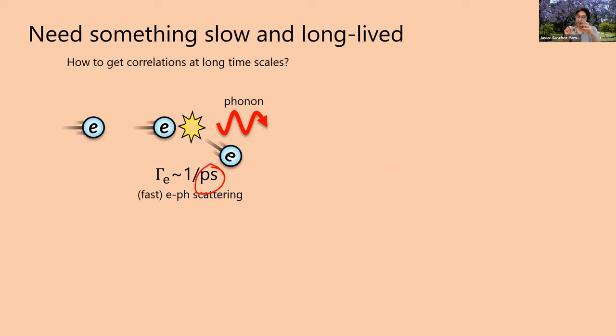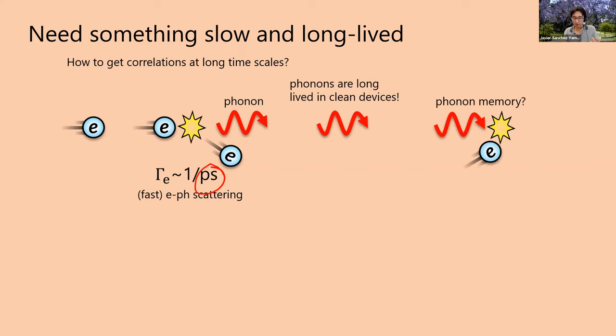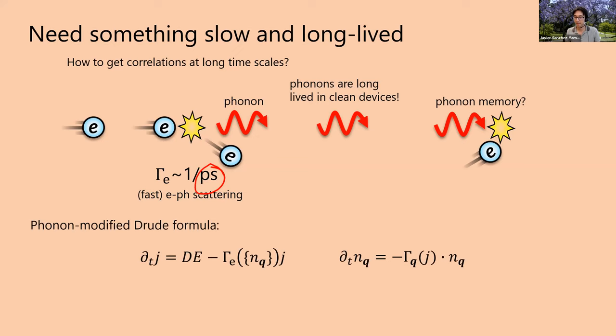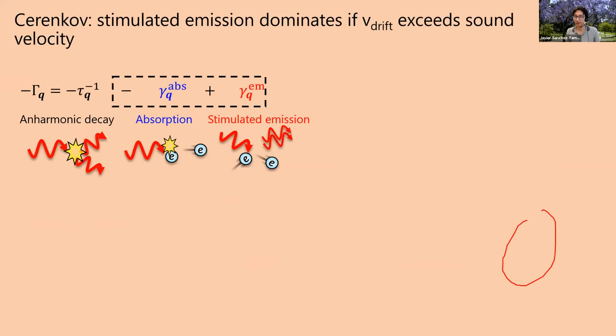But an electron can emit a phonon, and that phonon can live a really long time because you have a very clean graphene device. And so what we were thinking about is, what if this phonon lives for some long period of time and then interacts with some other electron? Could that build up some correlations and some noise over long time scales? And so, yes, indeed, something like this can occur. And it has an effect which is akin to Cherenkov radiation of light.